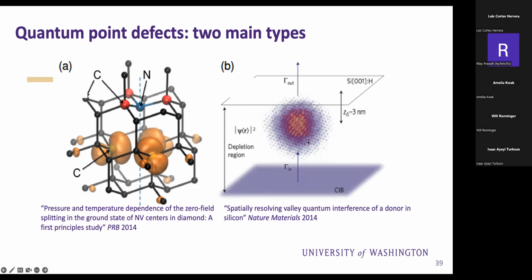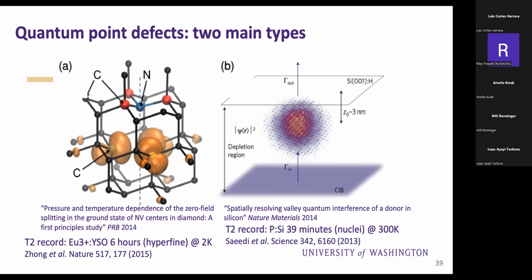People in both camps like to say why their defects are great. I would say that the numbers kind of indicate you can get good defects in either case. The T2 record for a deep level system is in the rare earths at 6 hours for a hyperfine transition at 2 Kelvin. The T2 record for phosphorus in silicon is 39 minutes. Again, this is for the nuclear spin memory.